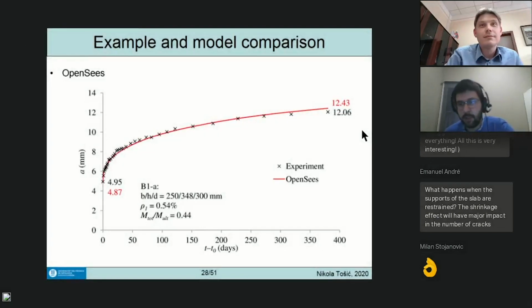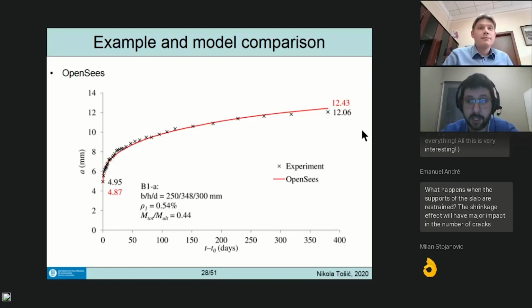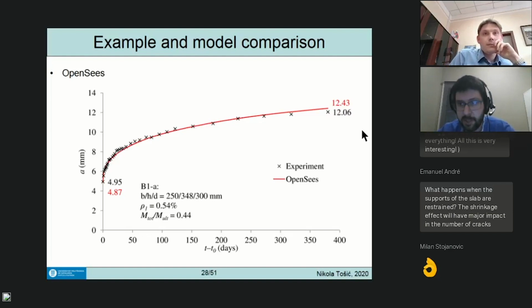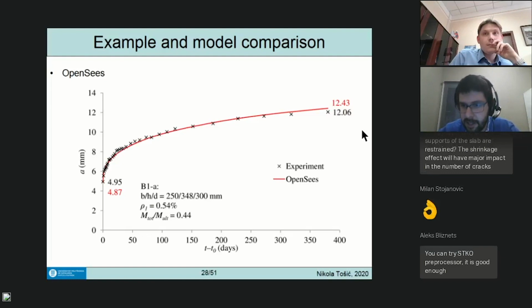Okay, when we apply this model with all of the inputs, and there's no reason for me to show you the input files if you're not using OpenSees, but this is the result we get for OpenSees. So it's using everything measured, okay? So the inputs are the measured compressive strength, the measured tensile strength, modulus, creep, and shrinkage. So everything is from the experiments, okay? Because we really want to test the model. We don't want to introduce new uncertainties by predicting things from compressive strength, okay? And we see that it's perfectly capable of capturing the evolution of deflections, of getting the curve right, even the initial and final deflections.